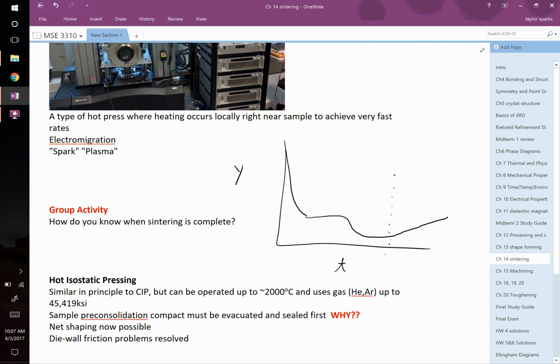Because you're doing this at high temperatures and you're applying the load, 5 minutes is a typical hold time for these things. So really, really fast. And then when you see it starting to go up, kill the power. Maybe you don't want to just kill the power directly because then you might thermally shock it. So sometimes they slowly cool it down. How do they cool these things? How would you guys cool it?